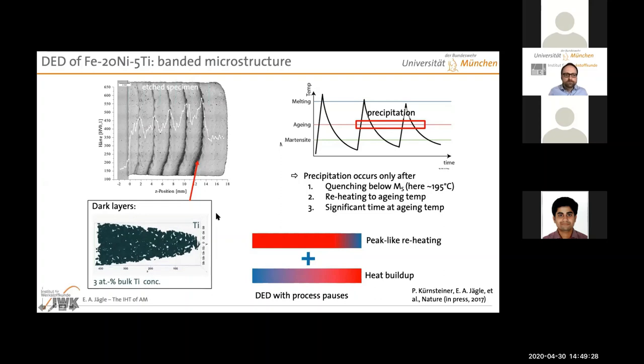Okay, is this a slice from a cube? Yes, or from something cube-like. So the thermal gradients are much higher on the outside, near the edges of the cube, than in the center, and so you see a lot more darker region on the sides. I think this is the reason why the side has the darker layer going down further than in the middle. The fact that it is bent overall has mostly to do with, ultimately, also a result of the thermals. Why do we see this drooping at the sides? It's because the melt pools on the outside are flatter than on the inside. And why is that? Well, it also has something to do with the thermals. Okay. But that is basically a problem of the DED process. I don't want to speak badly of our colleagues who made the sample, but you have the same process parameters everywhere, for every layer and for every track inside the layer. And that's what gives you this problem.